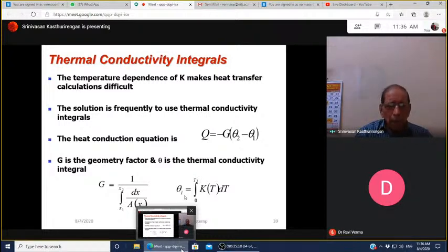Now, thermal conductivity integrals are normally considered for making calculations. Because we know very well the thermal conductivity depends on temperature, the heat transfer calculation becomes rather difficult if you try to do it directly. So what we do is make use of thermal conductivity integrals. The heat conduction can now be written like this: Q is equal to minus G into theta 2 minus theta 1. In this, theta is the thermal conductivity integral, theta i is equal to the integral from 0 to Ti of the thermal conductivity K multiplied by dT. So this is the thermal conductivity integral term.